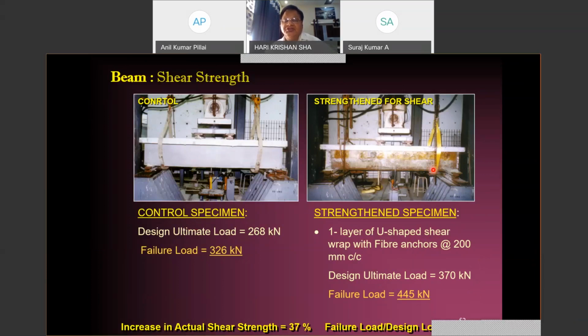And when this beam was tested, the failure load was increased to 445. So you can see that there was a significant increase from 326 kilonewton to 445 kilonewton, with an increase in actual shear strength of the order of 37%. So with a single layer of U-shaped shear wrapping, there was an increase of 37% in shear strength under shear.